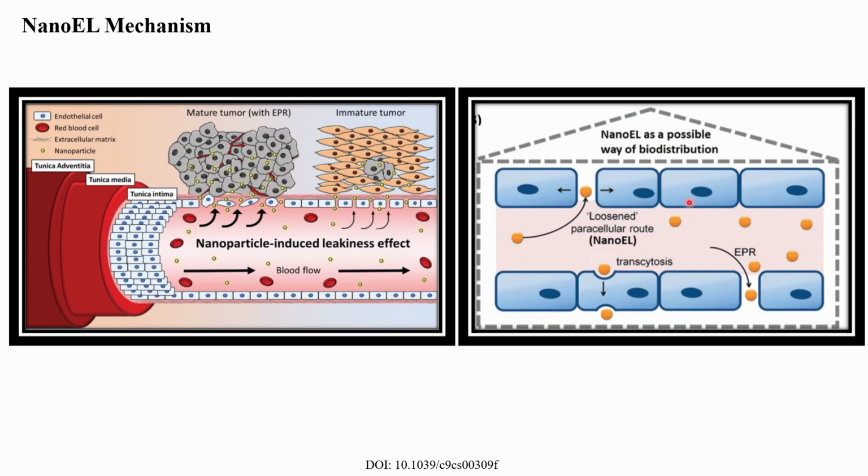Mechanism behind NanoEL. The NanoEL effect relies on disrupting vascular endothelial cadherin, a key adhesive protein between endothelial cells. Actin remodeling and cell retraction follow, creating micron-sized gaps between endothelial cells. Several studies since the discovery of NanoEL have focused on the intrinsic abilities of inorganic nanoparticles. The optimal size, surface charge, and density of nanoparticles play pivotal roles in controlling endothelial leakiness.